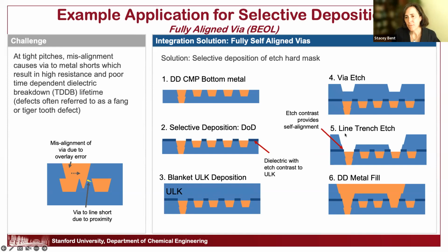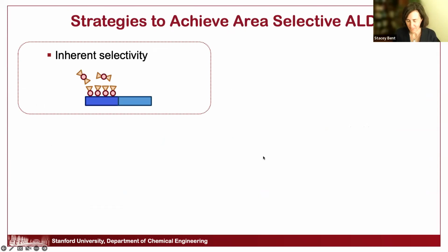And in your etching steps after, if you have a little misalignment, you're okay because you have already put in here this dielectric with etch contrast, and then you do the metal fill. So this is probably going to be among the first applications of selective deposition. How does one do that? Okay, I inserted a picture in the PowerPoint, but how does one actually do that?